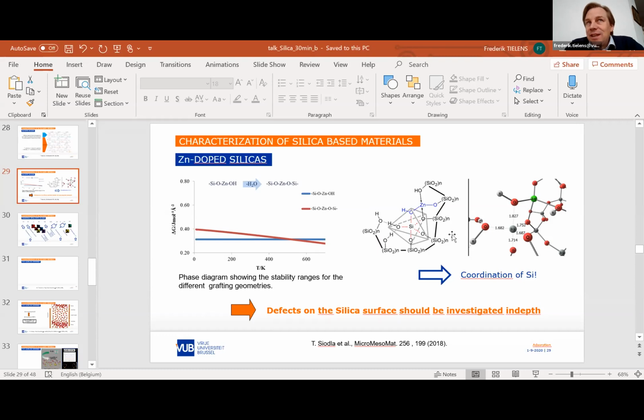But at the end, I want to say something that is also in my benefit: even if we didn't do the dispersion corrections, let's say 15, 20 years ago, we see that the results in these structures, which are quite ionic, don't change so much. So qualitatively, the conclusions I made so many years ago are still valid. This makes me quite happy. But of course, now we use the dispersion correction to make it more precise. We should follow the evolution of the calculation levels.